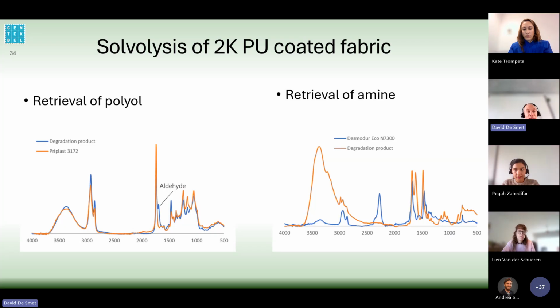At the left, you can see the infrared spectra of your original polyol, which in this case we used was 3172, and then of the retrieved polyol, so your degradation product. We can see that the peaks are almost the same except for one peak. I also indicated that on the slide, which we saw was an aldehyde peak.